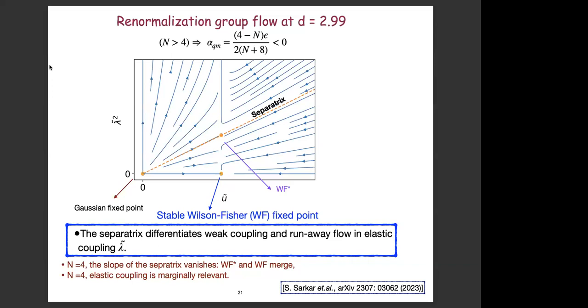But above this line, the flow is again away from this Wilson-Fisher fixed point, that is, it flows towards strong coupling. So what we can infer from this plot is that, first of all, the separatrix basically differentiates between the strong coupling and weak coupling regime. And we will see in more detail what is actually happening in these two cases, whether there is a structural transition or not. And also for n, when n goes to 4 in this case, we will see that